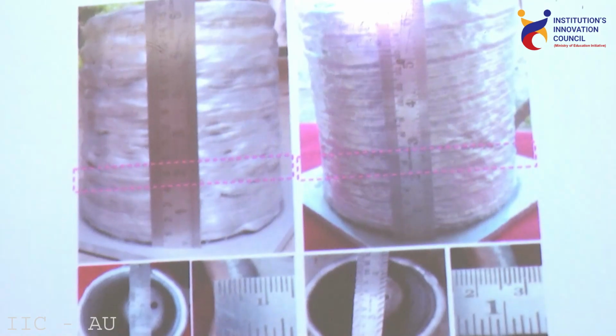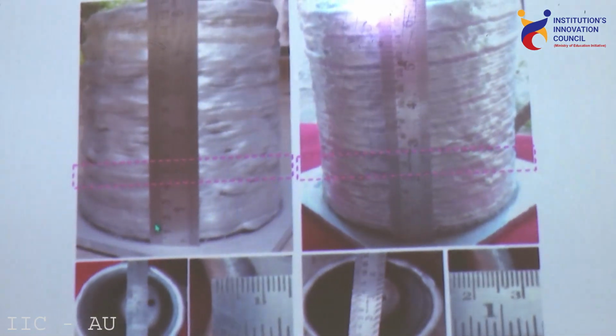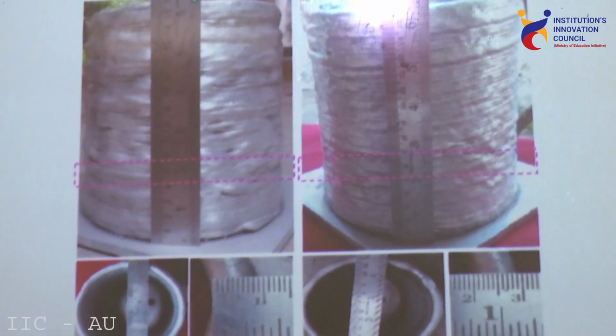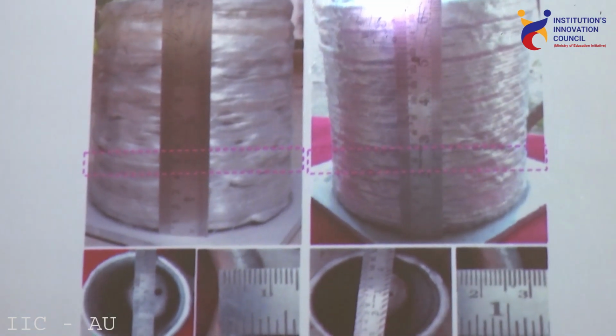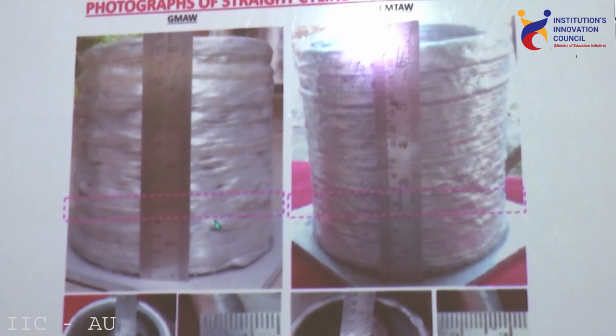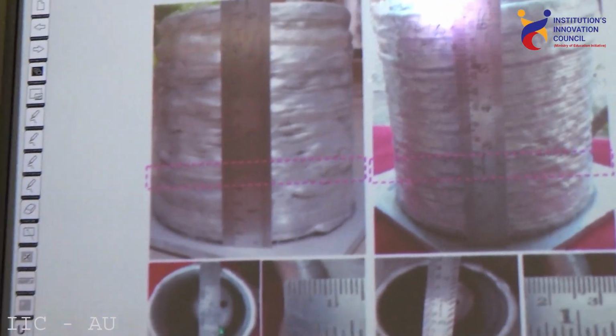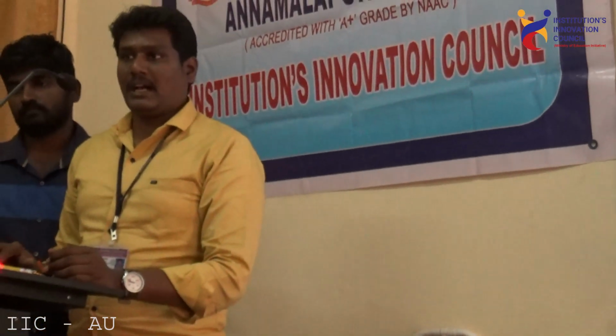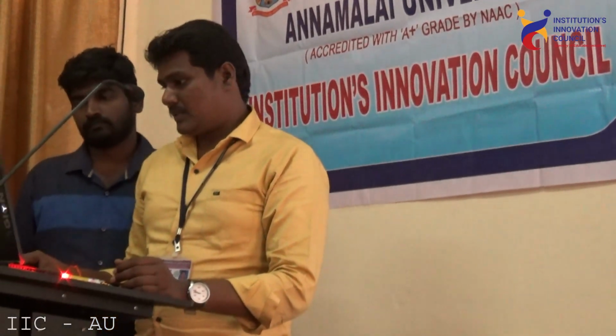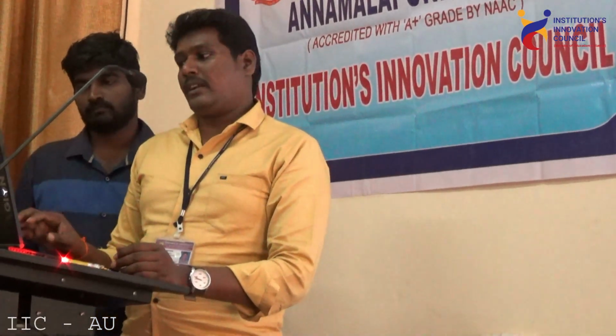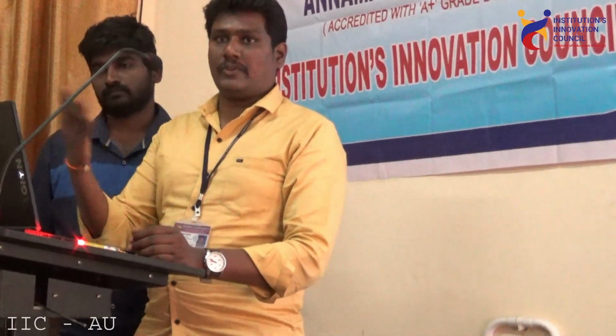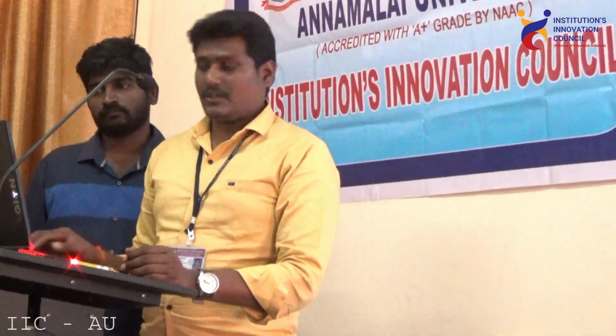We have developed a component which is around 160 mm, that is 16 centimeters. This is the actual height of the component, which is produced by two methods: one is the GMAW process and another one is the CMT process. This is the diameter of the component which we have developed, around 90 mm internal diameter and 7 mm thickness. This is the component after machining, the view for both GMAW and CMT.